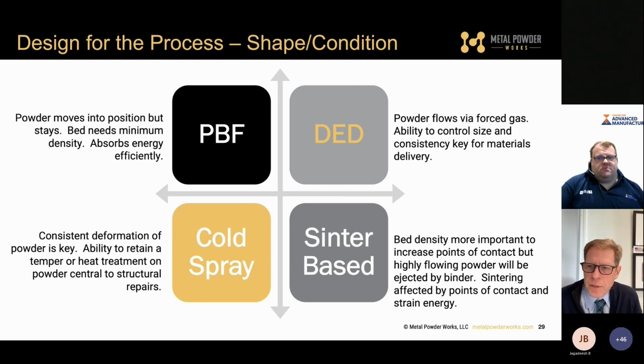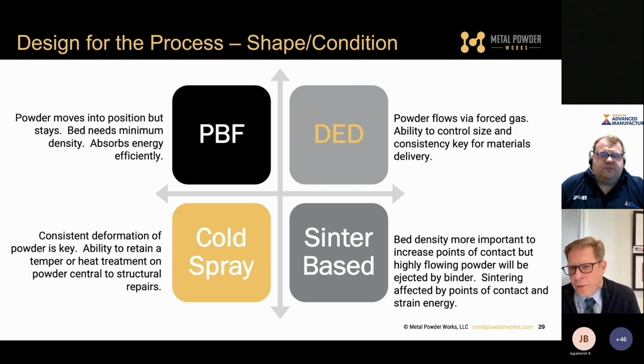On directed energy deposition, we talk about powder flow via forced gas. So it's a very different situation than everywhere else. Similar to cold spray, it actually doesn't desire a spherical powder in the first place. For DED, the ability to control size almost ties to surface finish pretty directly, but you need consistency for this material delivery.